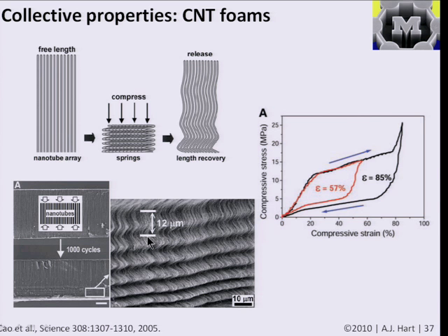And the bottom line here is they show that this can be a very effective energy-absorbing material. It can deform by very, very large strains. In this case, their initial cycle was 85%, and this is the loading path. And based on the buckling, you see these. This is classic foam-like behavior. You see ripples every time one of these buckles generates. And then when you unload it, there's basically a big empty space here, which is a lot of energy absorption.